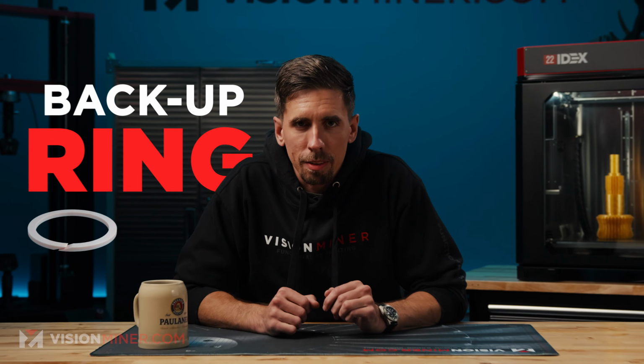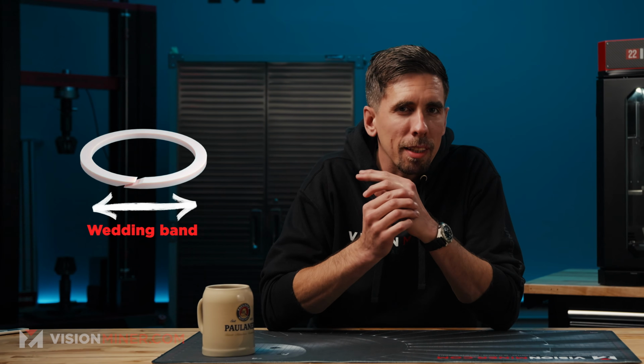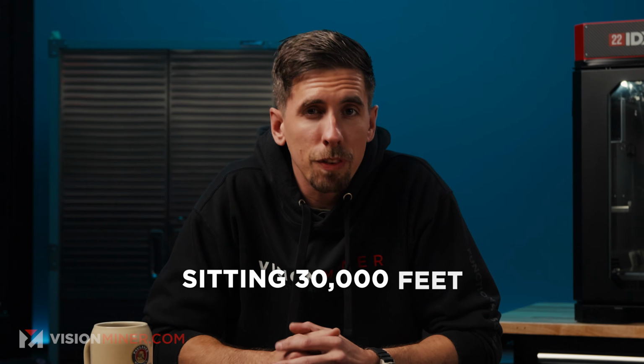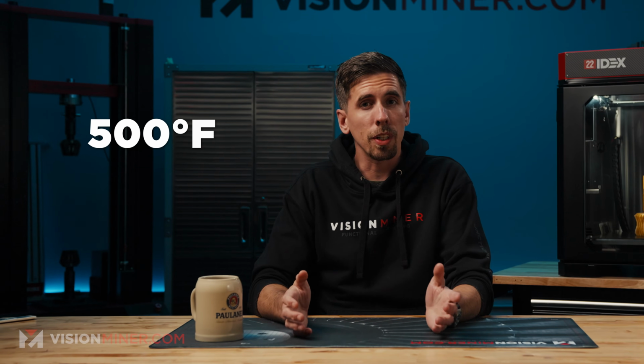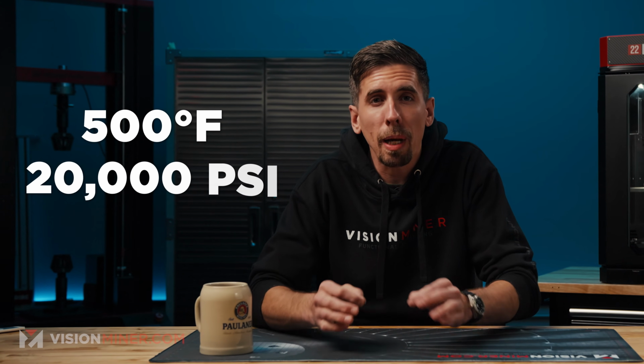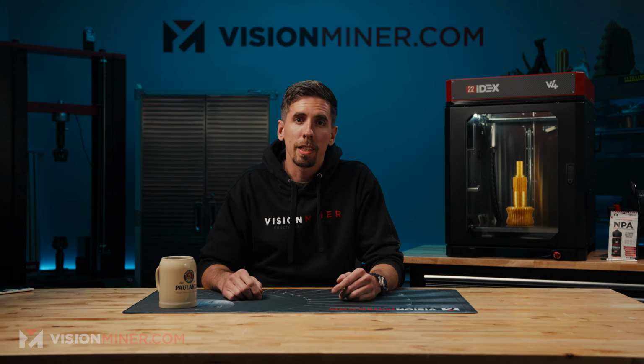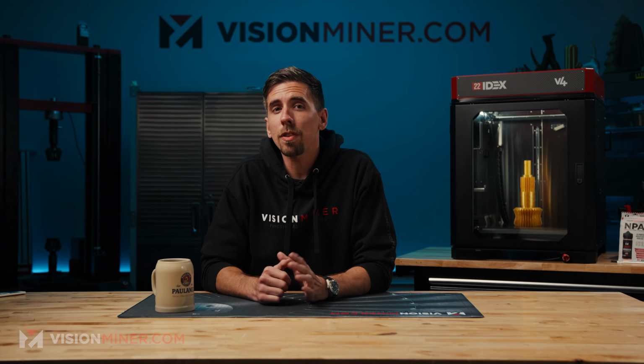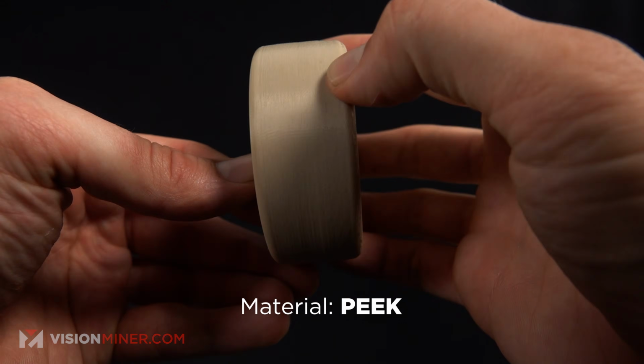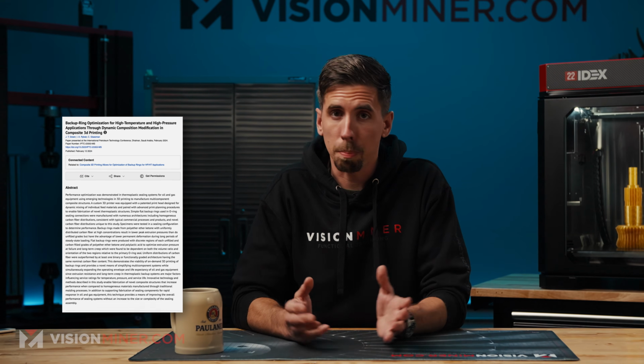A backup ring, about the size of a wedding band, sitting 30,000 feet underground, 500 degrees Fahrenheit, 20,000 pounds per square inch. If it fails, the seal fails, and the entire pressure assembly goes with it. Now picture a research team at the University of Texas, El Paso, working directly with Halliburton, 3D printing those rings out of PEEK. And the paper, it's published. Halliburton's name is on it.